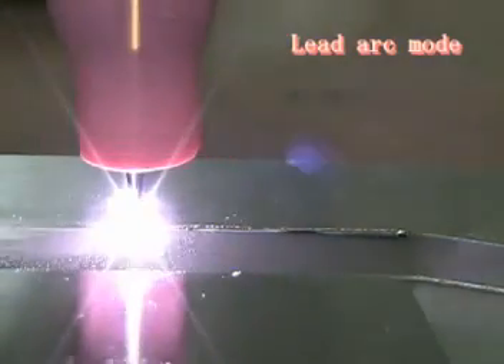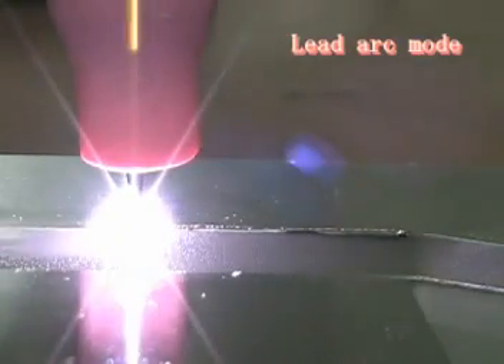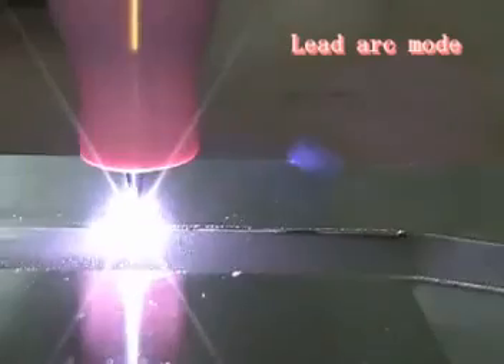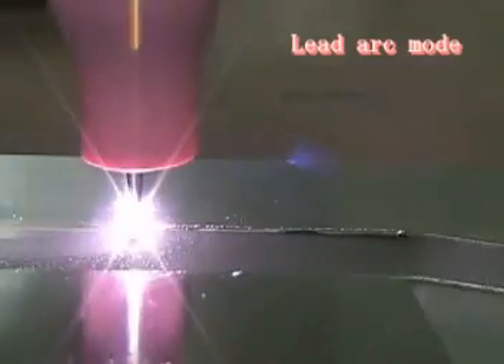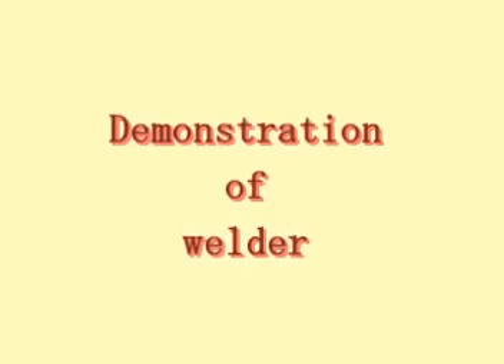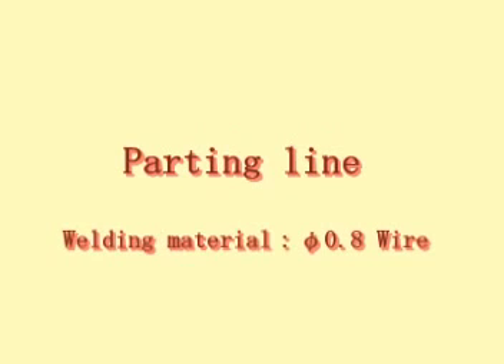By applying a minute 2 ampere arc to welding points prior to actual welding operations, you can easily weld the appropriate points. Now, I will show you actual welding operations using a welding machine. During the demonstration, you will see that an operator uses a copper plate. It is used to avoid shrinkage by having the copper plate absorb the excess heat during welding operations.